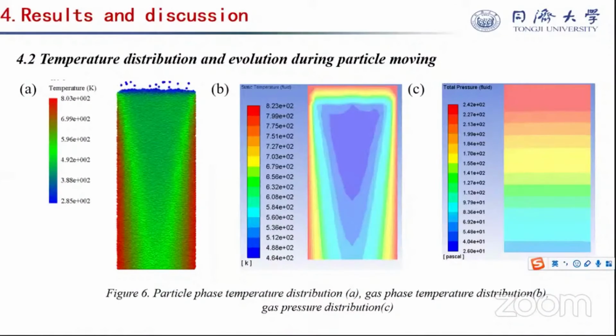In the figure on the left, illustrating particle phase temperature distribution: once particles fall into the reactor, the temperature of the particles rises sharply, and then slowly, and the temperature of the particles exiting the reactor is relatively uniform.